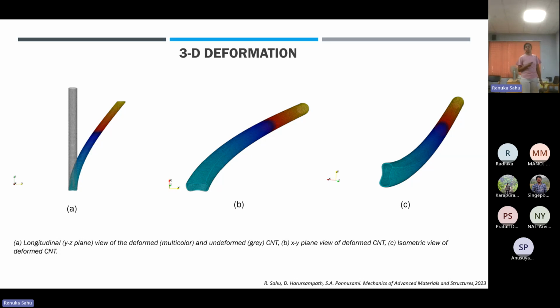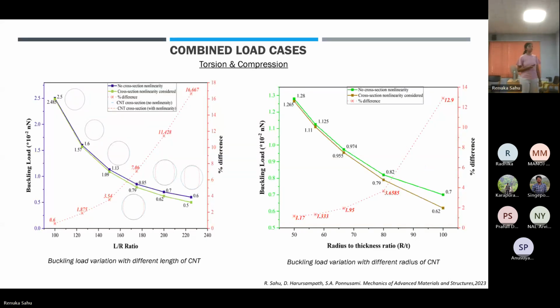Similarly, we did the torsion and compression case. Here, instead of the bending load, we apply a twist. Again, for this case we studied the variation with slenderness ratio and with radius-to-thickness ratio of the buckling load, and the same conclusion can be derived: for higher length of CNT and higher radius-to-thickness ratio, there is a larger difference between the nonlinear cross-section and linear cross-section cases.